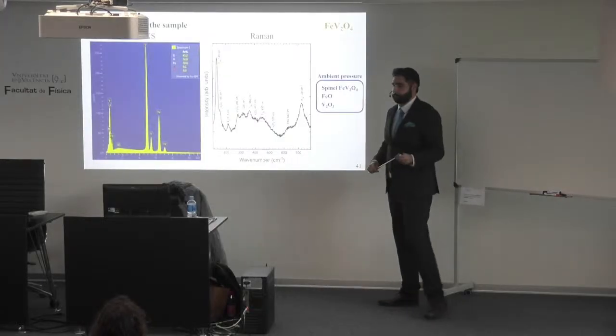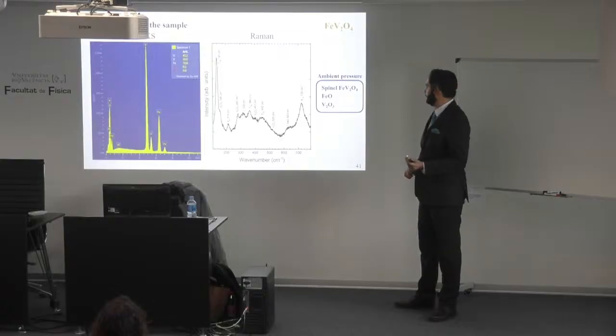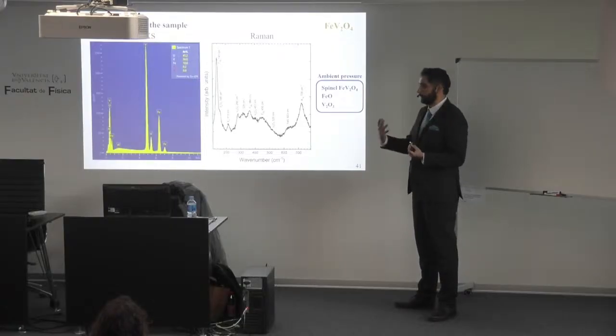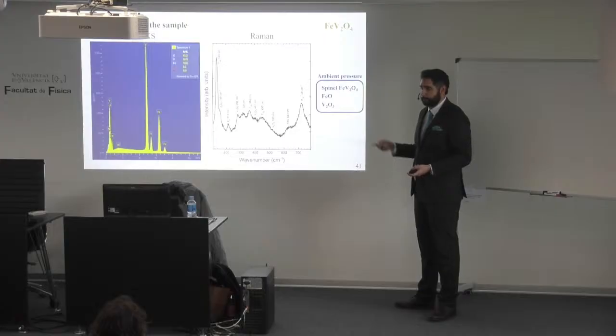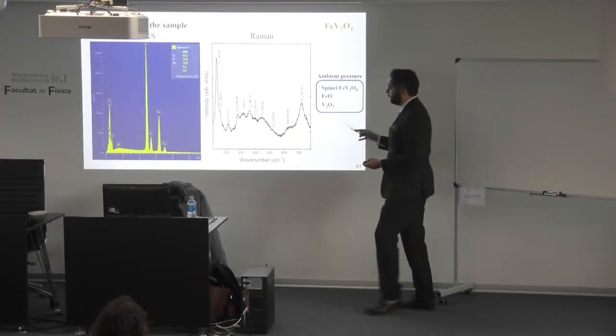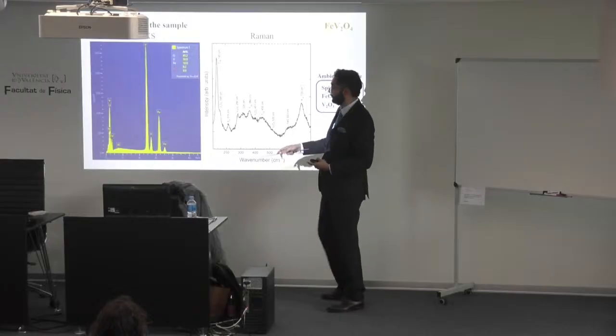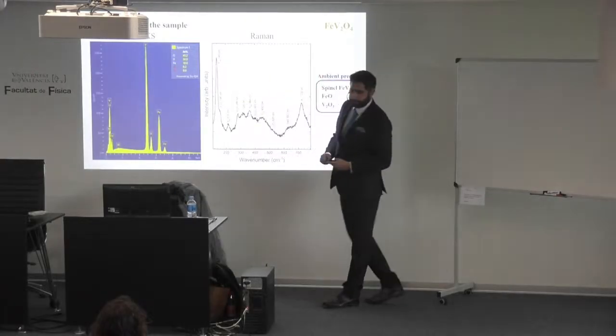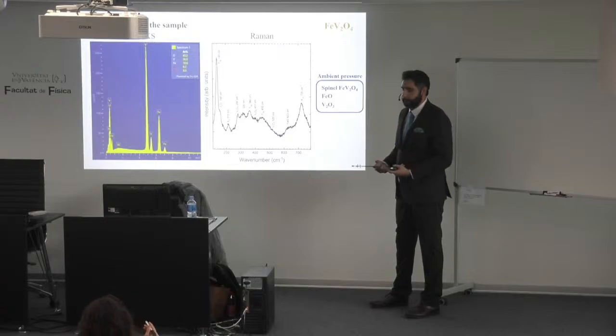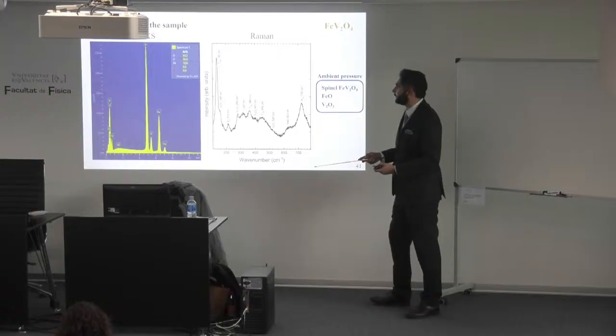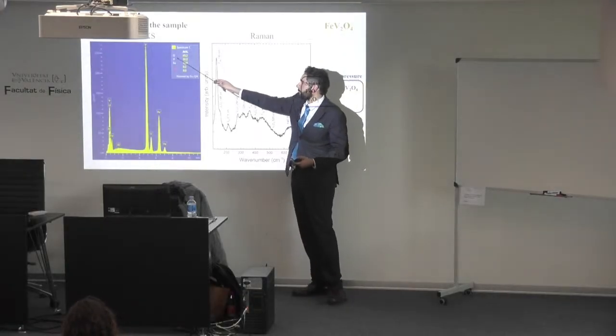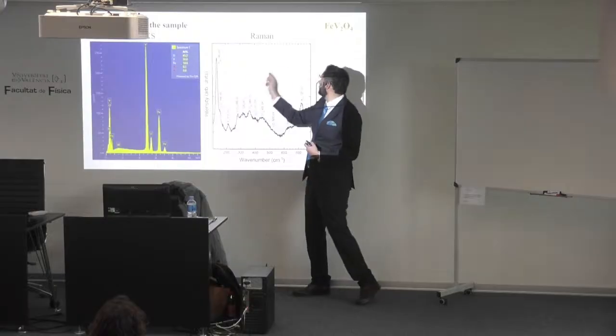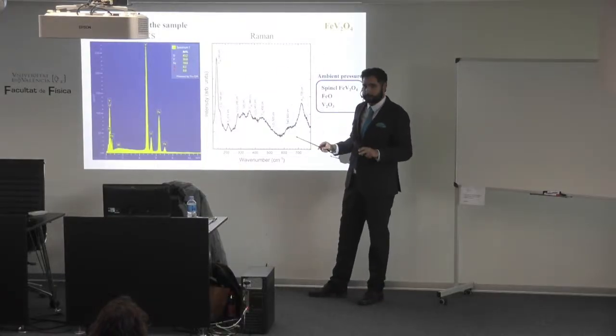And now the spinel iron vanadate. In this case, we saw from an XRD at ambient pressure that we had extra contributions from other compounds that were not related to the expected one. So we had to add some probes in order to identify them. One of them was the EDXS, that is telling us which elements and in which ratio are found in the sample. So it's just oxygen, vanadium, and iron in this stoichiometric relation. So it has to follow this rule.